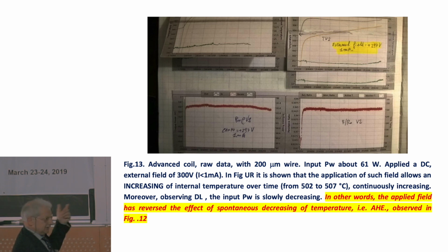So we think, okay, you need non-equilibrium. We use the positive voltage, it increases, okay. We stop, we put 0 voltage, the DC stops. We decided to apply a negative voltage. When we apply a negative voltage, the temperature has a big jump, but then a wide break. It was too strong a reaction. It was completely unexpected. I supposed it would reduce the power, but it is more.